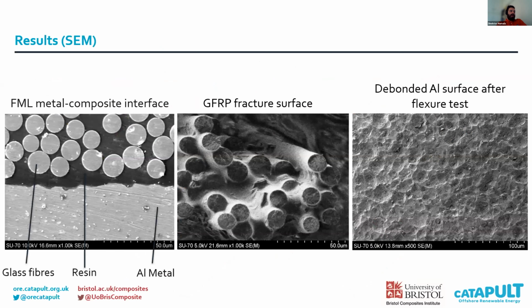In this slide, you can see some SEM micrographs of the thermoplastic fiber metal laminates, highlighting the good adhesion and bonding between the composite and the metal phase of the tested FMLs, as shown in the figures on the left side. Also in the center, you can see the fully wetted fibers, pointing out the strong adhesion between the matrix and the glass fiber that was achieved.